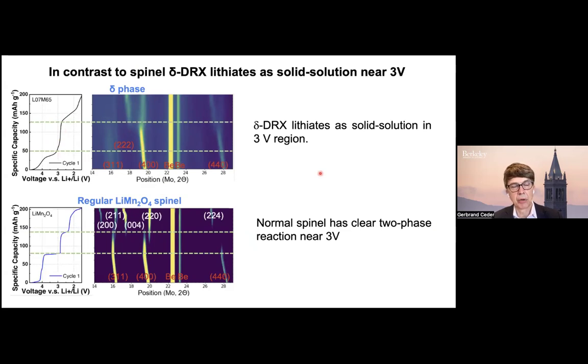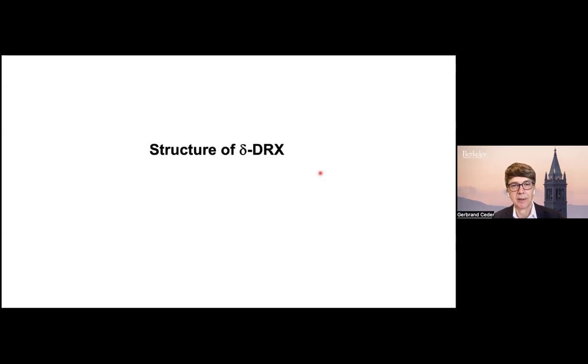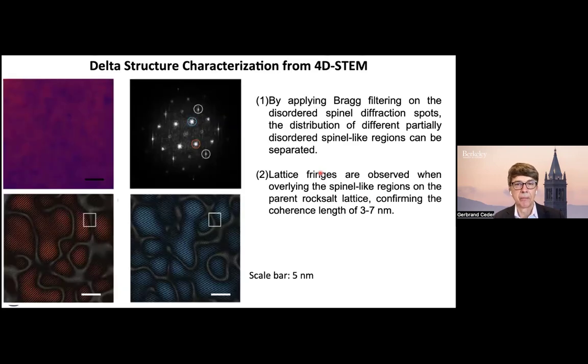So the question is, what is the structure of this material that makes the material so good, and could you induce it without cycling, right? Because nobody wants a battery that you have to kind of try out for 20, 30, 40 cycles to make it actually work to your advantage. So the structure of delta DRX was a bit of a puzzle. We had certainly historically known from theory that when you reduce manganese from 3+ to the 2+ state, manganese is quite mobile in rock salt environments, and that's also why you can never make a layered lithium manganese oxide cycle, because the manganese just moves all over the place. And obviously the ground state that it wants to evolve to is usually spinel. And so it's no surprise that what it actually forms is related to spinel.